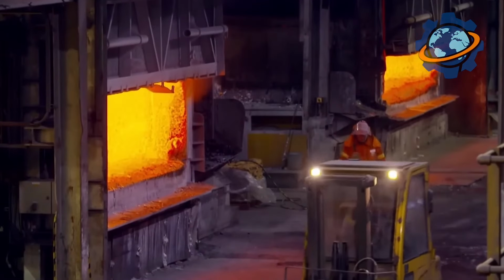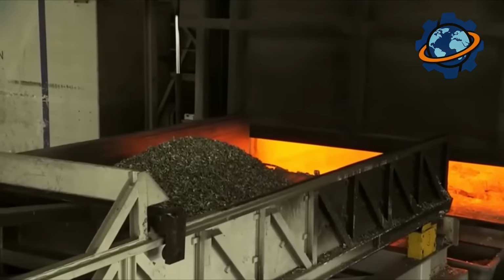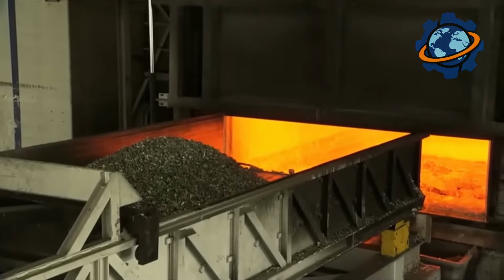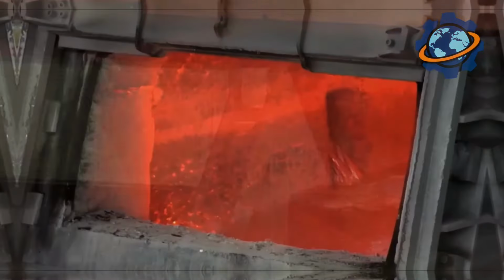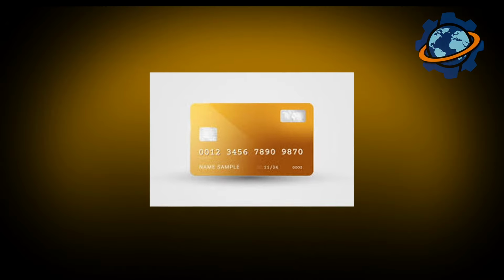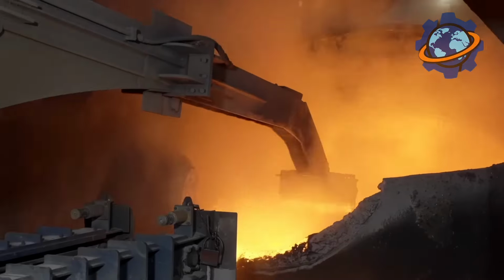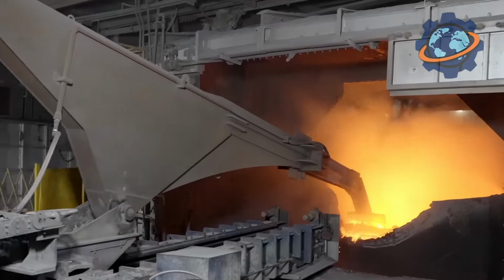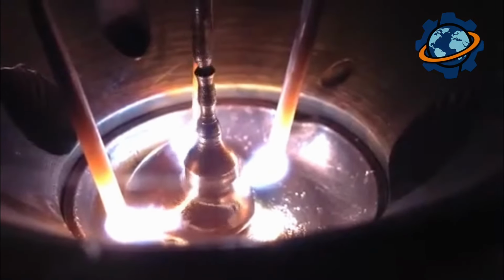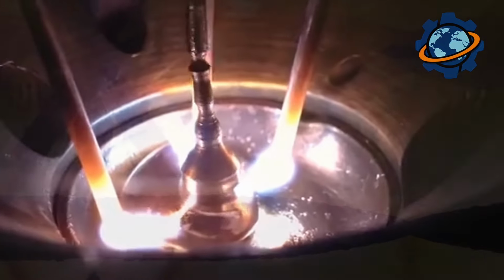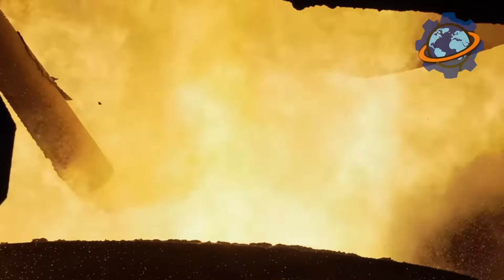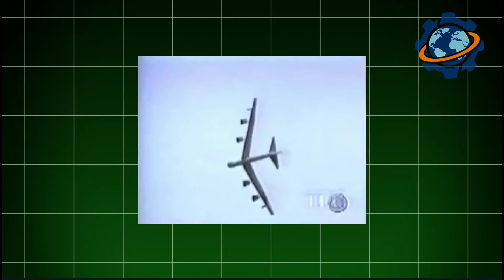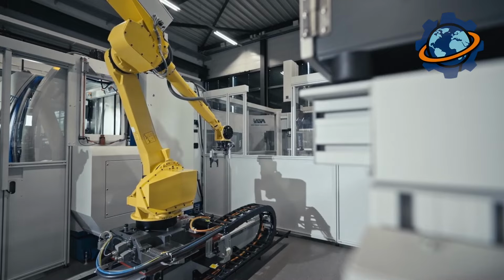These molds contain passages narrower than spaghetti strands, designed to cool blades from inside during operation. Some channels measure just 0.008 of an inch across, thinner than credit cards. Manufacturing these passages requires such precision that lasers verify every dimension. One blocked cooling hole means blade failure at 300 degrees lower temperature, the difference between safe flight and catastrophic engine disintegration at cruise altitude, scattering turbine fragments through the fuselage like shrapnel.